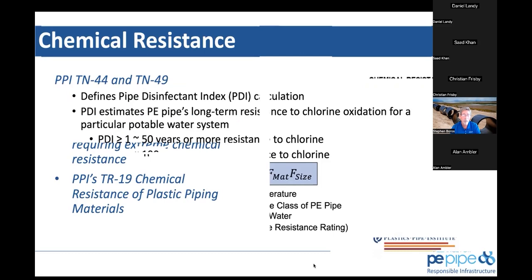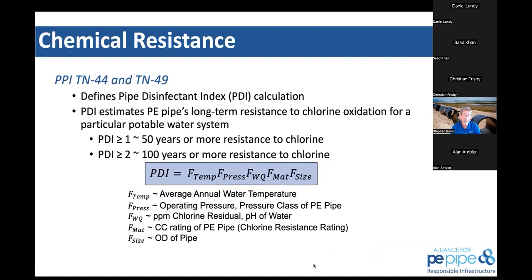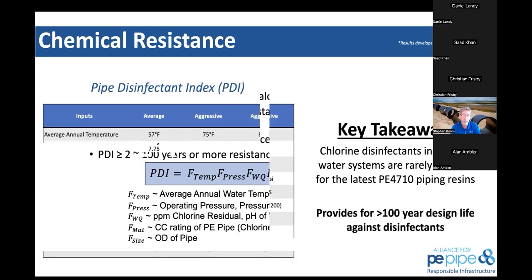For municipal systems, though, we're really worried about disinfectants. So disinfectants, or oxidizers, if you will, are used to keep our water safe, right? And every material is affected by oxidizers in one way or the other. It just depends on what you're doing with it, whether it's a chlorine disinfectant, or whether it's oxygen from corrosion for iron pipe. But I can tell you, every thermoplastic is affected by disinfectants. Doesn't matter what it is. It's going to be affected by that oxidizer when it's exposed to it long term. For polyethylene materials, we purposely now formulate those for long-term resistance to chlorine residuals in water systems. So this was probably a 5, 6, 7-year project where we looked at and developed models for how to qualify polyethylene materials to give you this 100+ year service life.